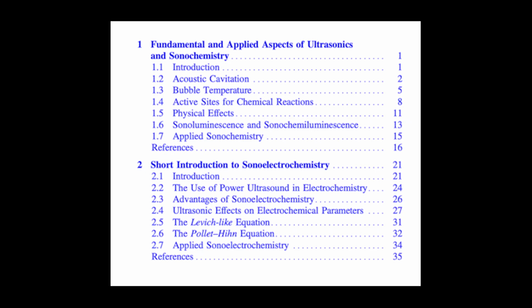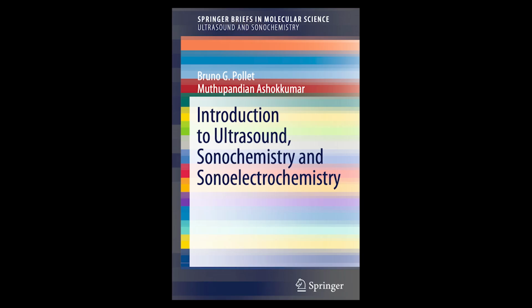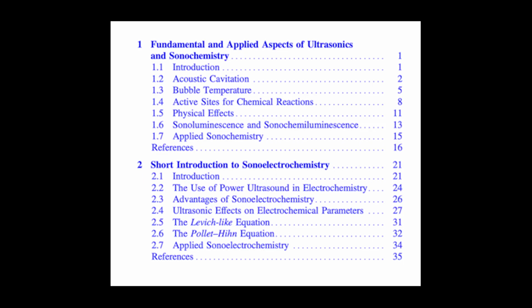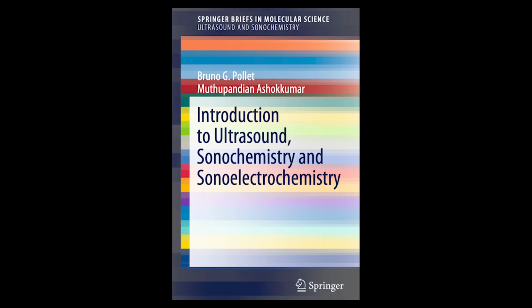Now, here's something I found really interesting in the source material. It notes that under typical power ultrasound frequencies like 20 kilohertz, even relatively large electrodes, millielectrodes, say with a radius bigger than a millimeter, start to behave electrochemically as if they were tiny microelectrodes, radius less than a millimeter. How can a big electrode suddenly act small? Isn't that cool? It's a fantastic illustration of just how dominant the local mass transport effects of ultrasound are. Microelectrodes normally have special properties, like high current densities, steady state behavior, because their tiny size naturally leads to very efficient, nonlinear diffusion of reactants towards them.